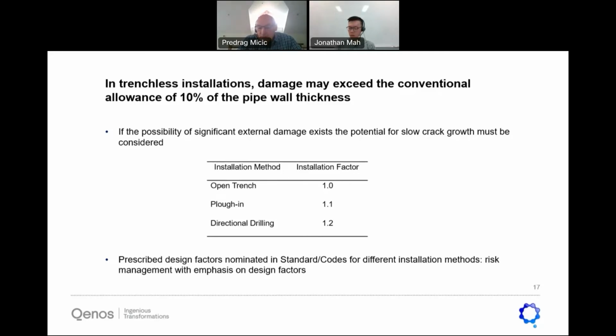They're explicitly goal setting and performance based, allowing provision to design pipeline based on a risk-based design. So the real risk, rather than managing the risk just by increasing the pipe wall thickness, that may not be the best integrity safety measure for the risk that exists there. And for example, for horizontal directional drilling (HDD) installation, the real risk is the presence of notches on the pipe surface that may have been incurred during installation. These notches present potential points for slow crack growth and progress to brittle failure, but also they can be deeper than 10% of the wall thickness as prescribed in the installation guidance document. But many of our current standards, 4645, you name it, codes of practice, they already have two ways to design: a prescribed way, and a risk-based design that you can choose to follow.